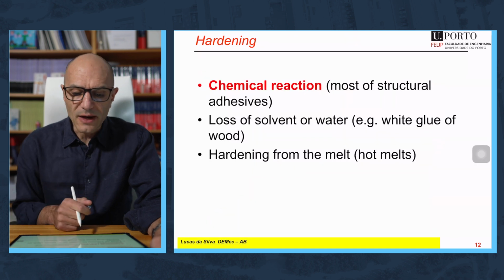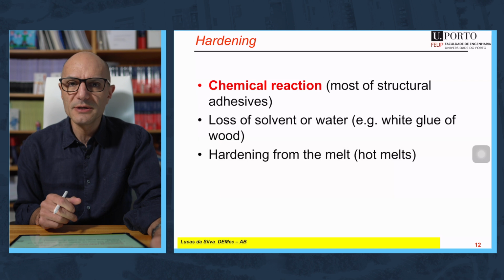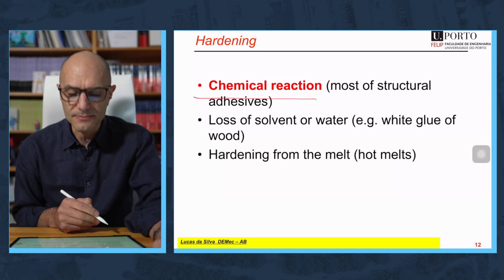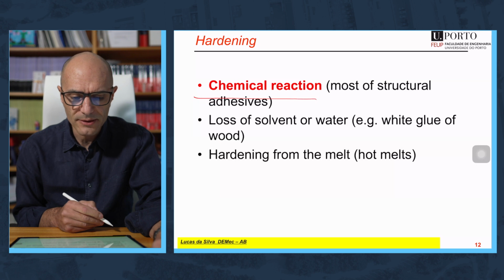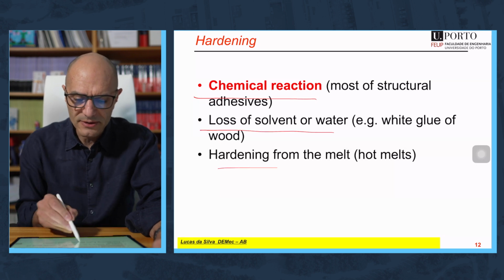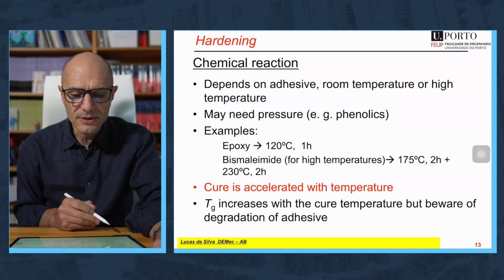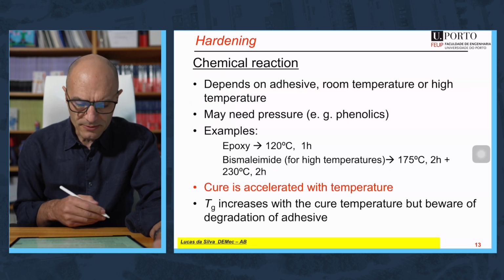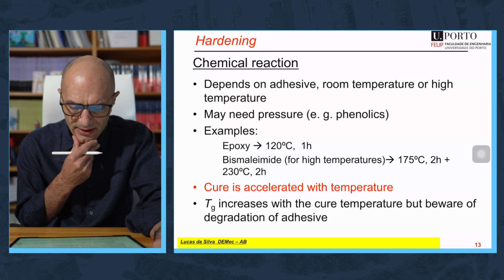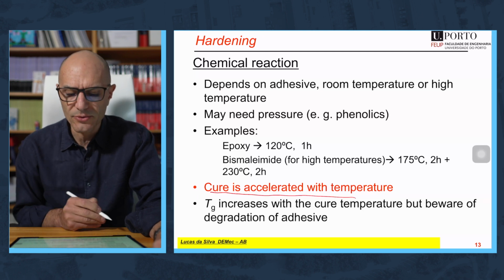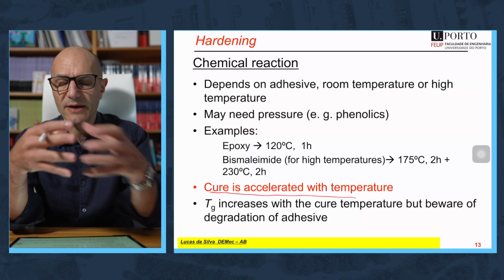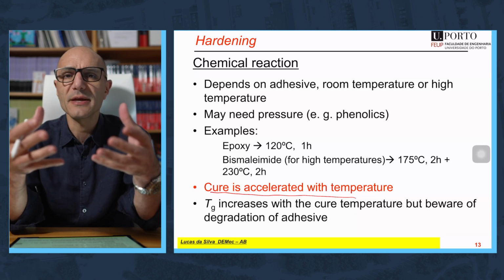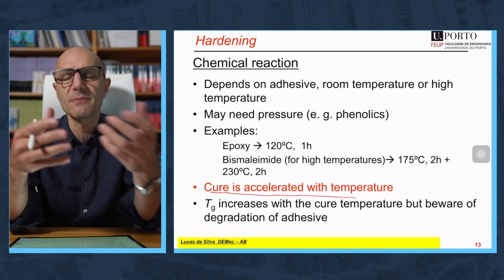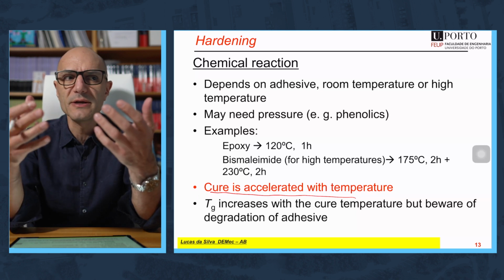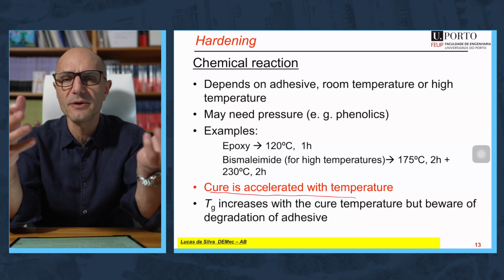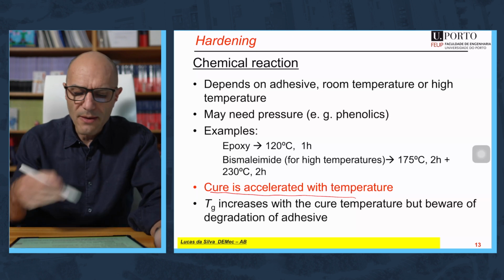And then comes the hardening. You already know that for structural adhesives, chemical reaction is the main way to harden the adhesive, but you can also have loss of solvent and hardening from the melt. About the adhesives that cure by chemical reaction, there are several points to bear in mind. For example, cure is accelerated with temperature, which is nice. For example, you might have a two-component epoxy adhesive that cures at ambient temperature, but it would take 24 hours typically. If you increase the temperature to say 120 degrees, then the time to cure would be much reduced.